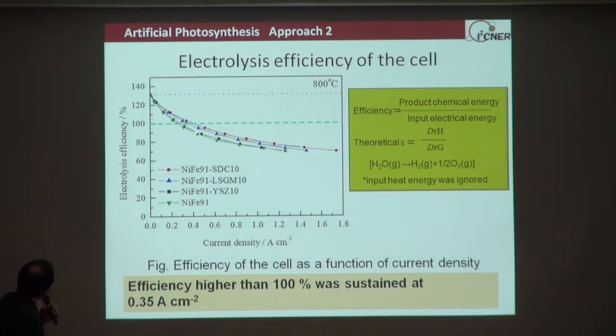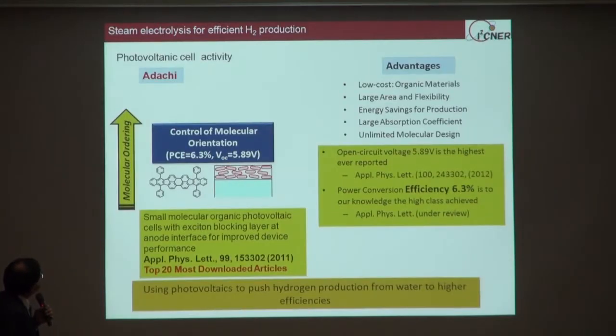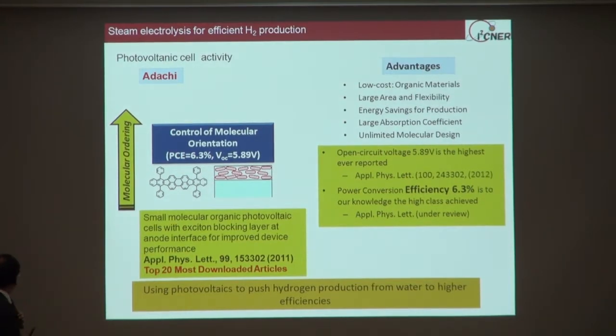And at this point, we call it the thermal neutral point, where no energy is requested to keep the cell temperature. But anyway, as you can see here, the thermal neutral point comes at 0.4 amperes per centimeter squared on these cells. And including the energies, the total energy conversion efficiency is close to 0.95 for this current steam electrolyzer. And this result was also introduced by Director Sophronis.